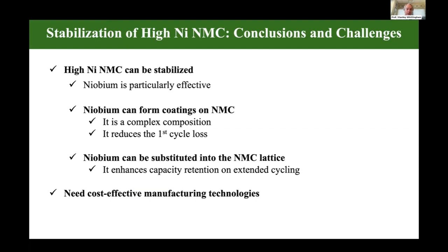So what we have shown here is that high nickel materials can be used. We can basically eliminate their reactivity, both with the environment. So these materials are more stable if you keep them in the lab than the pure, say, 80–90% material. We found that niobium is particularly effective. We haven't looked at all other materials, but most commercial NMCs are stabilized with one element or another. Typically, most common one is boron. Others are using aluminum, but we found niobium is most effective.